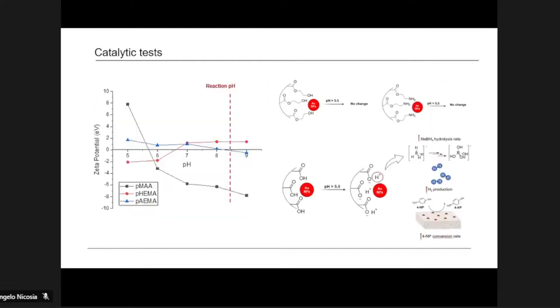So, when we have a pH upper 5.5, we have the deprotonation of the acid moieties to form an acid microenvironment around the nanoparticles, and therefore they contribute directly to the catalytic mechanism to increase the sodium borohydride hydrolysis, therefore hydrogen production, and so increase the nitrophenol conversion.